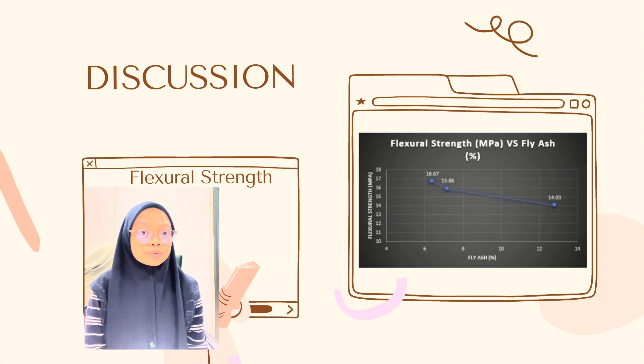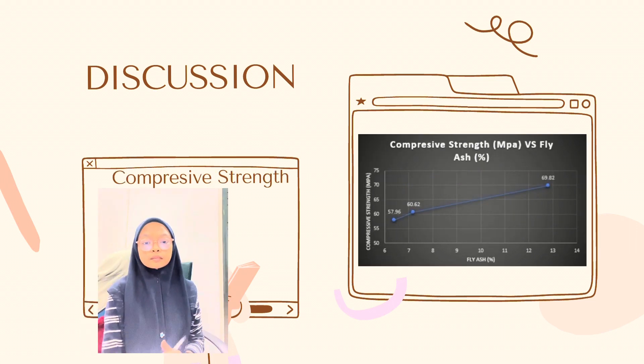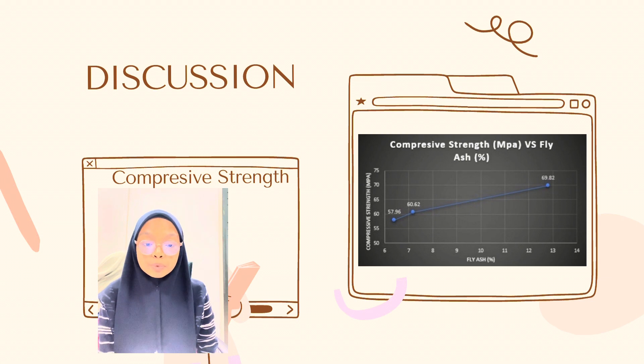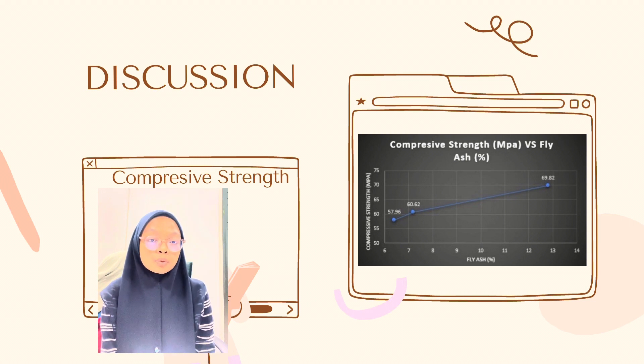For the discussion, I will explain about compressive strength, flexural strength, and split strength of polymer concrete. The 3 samples tested are 6.4%, 7.2%, and 12.8% of fly ash dosage. The first graph represents compressive strength versus fly ash for 12.4% of epoxy resin. The highest compressive strength for 12.4% was 69.82 MPa and the lowest value was 57.96 MPa. From the results, we can conclude that the higher the dosage of fly ash, the higher the compressive strength, as the 12.8% fly ash sample gave higher strength than samples 1 and 2 at 6.4% and 7.2% respectively.